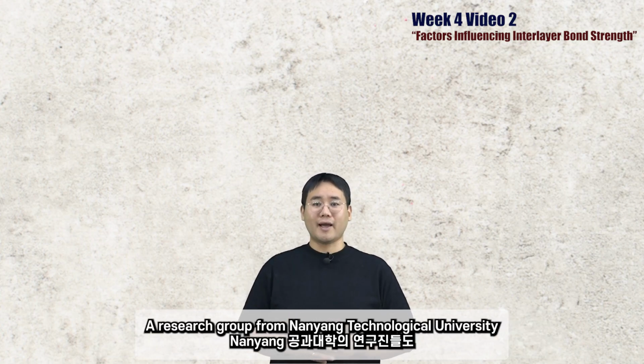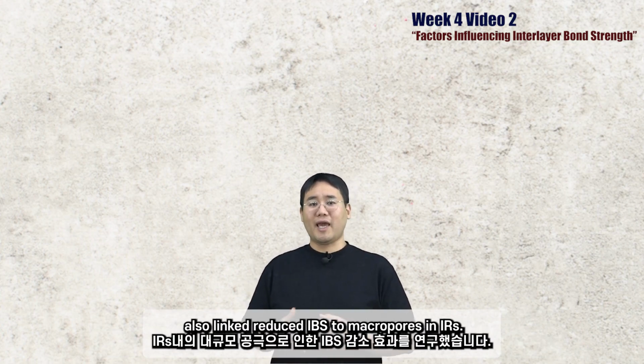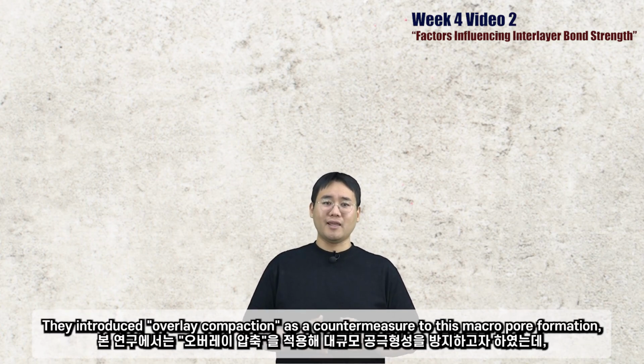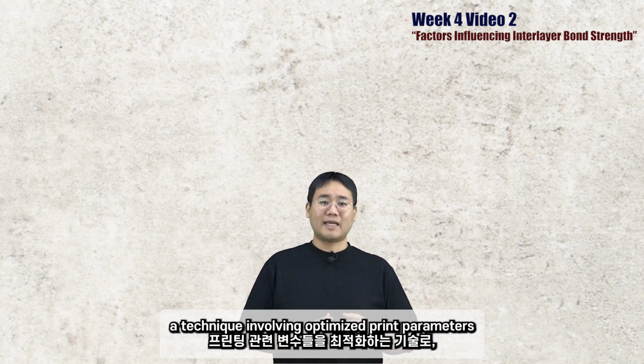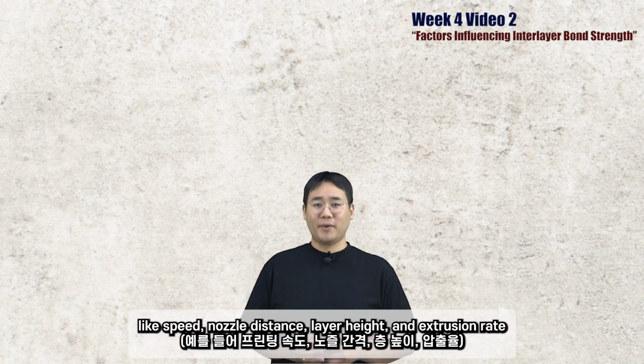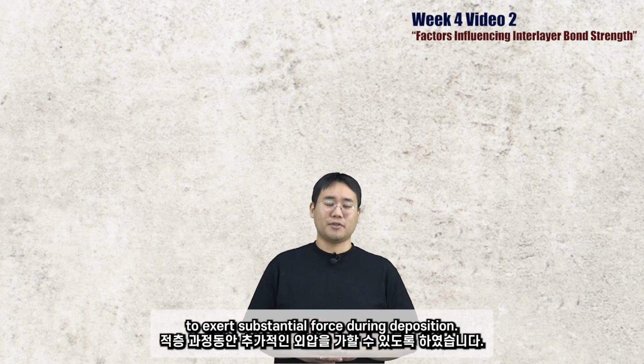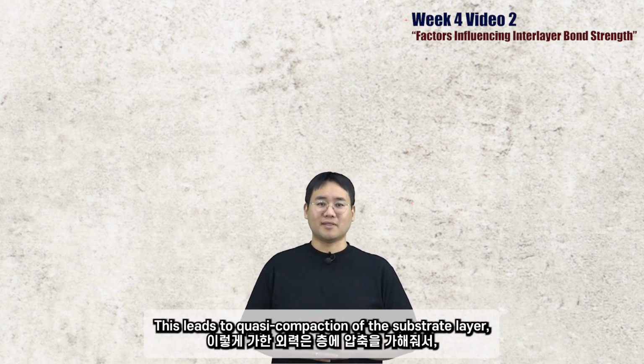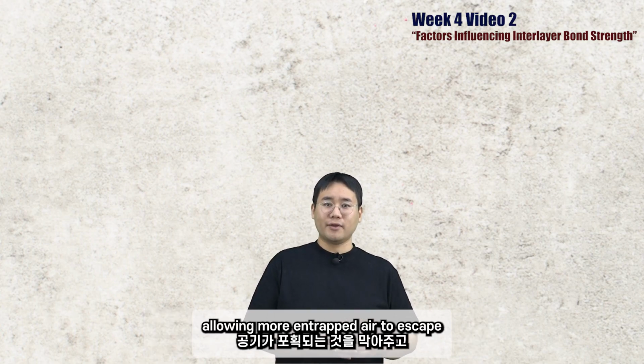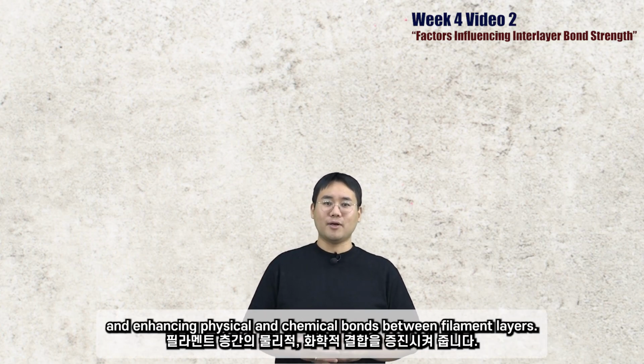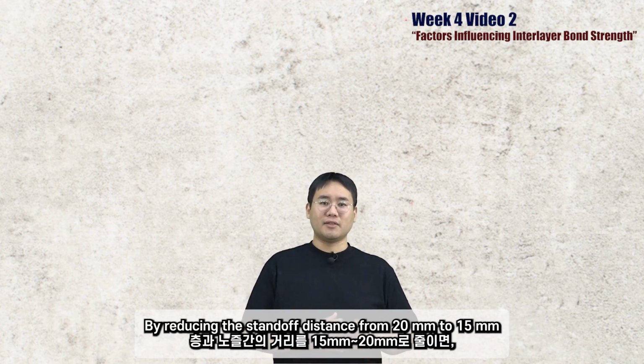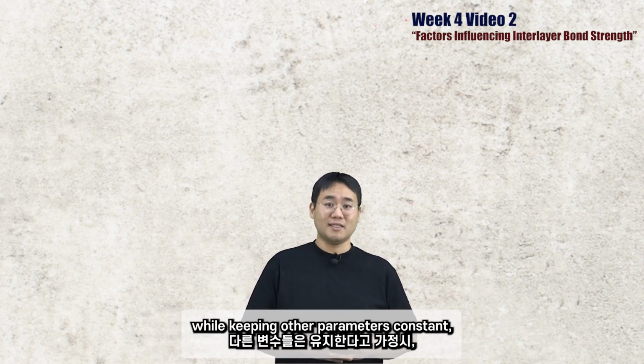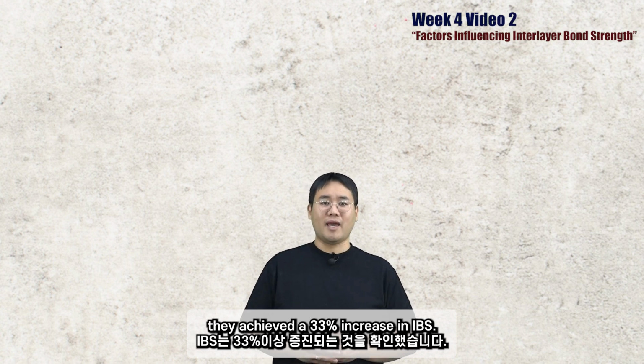A research group from Nanyang Technological University also linked reduced IBS to macropores in interlayer regions. They introduced overlay compaction as a countermeasure to the macropore formation, a technique involving optimized print parameters like speed, nozzle distance, layer height, and extrusion rate to exert substantial force during deposition. This leads to quasi-compaction of the substrate layer, allowing more entrapped air to escape and enhancing physical and chemical bonds between filament layers. By reducing the standoff distance from 20 mm to 15 mm, while keeping all the parameters constant, they achieved a 33% increase in IBS.